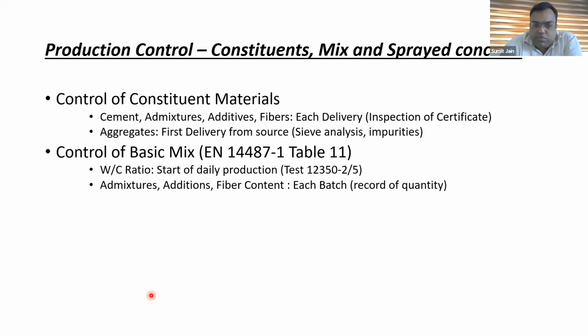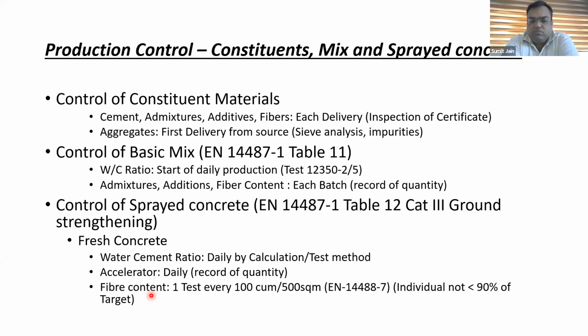Next, we check the basic mix. We check the water cement ratios, and these are to be checked daily when the production is started. Whatever is mentioned in the mix has to be achieved in the batching plant. Then we control the basic admixture, additions, and fiber contents. These are recorded batch wise in terms of quantity.